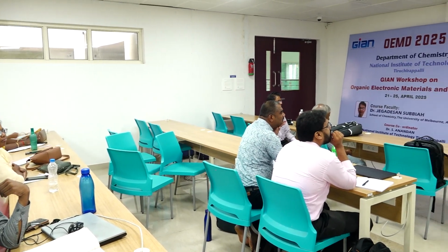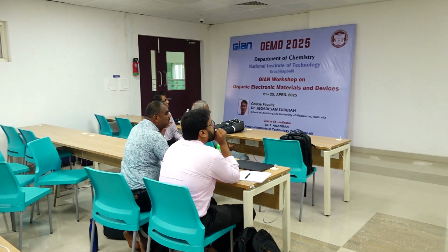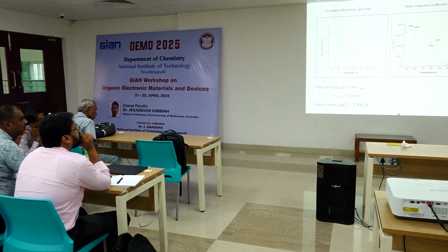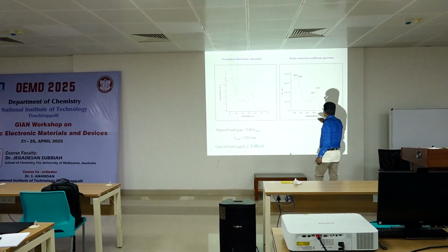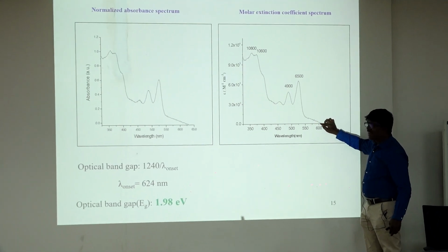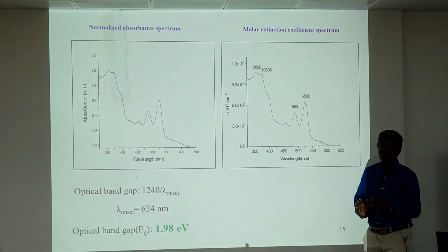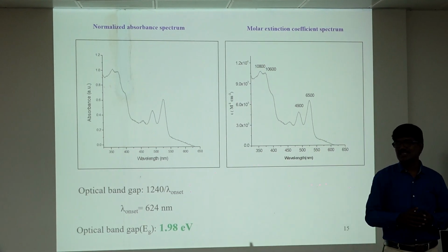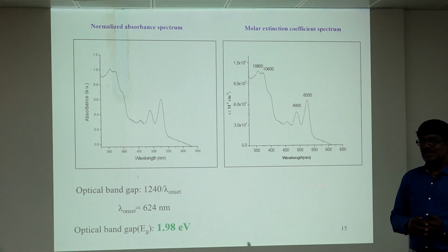Yeah, we have to extrapolate only. This is the absorbance graph, lambda max. You understand? If you take transmittance mode, you are doing the one. In the case of your Tauc plot band gap, we are doing the other side. For the band gap calculation, we extrapolate in a different manner. Since it's liquid state, the onset line can start from 800 and come here. The point where it increases, we call the onset. The absorbance where it goes from 0 to increasing, we call the onset. That's the value we can use in liquid state mode.